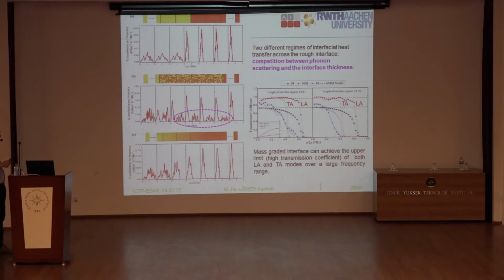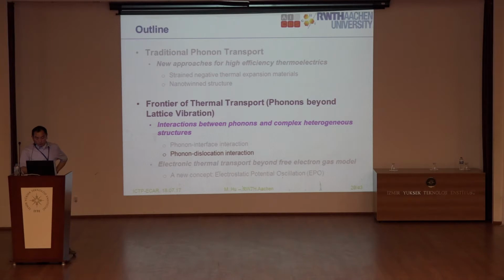So we use our recently developed frequency domain decomposition method, and then you can decompose the heat flux as a function of frequency, and then you can take a look at the different interface and what's happening there. And then the determined mechanism I don't have time to discuss here. I just skip this. So now I will quickly talk about the phonon dislocation interaction.